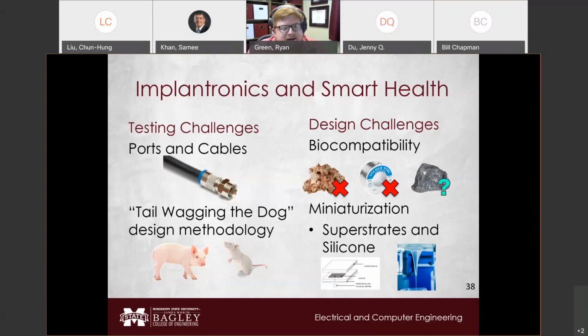Well, the permittivity of the material that you're implanting your device in is so high that you can effectively miniaturize your antennas pretty well if you were just exposed to that material. And the superstrates and the silicone have a lot lower dielectric property than the surrounding material, meaning that while you're trying to minimize your antenna, it's actually not the smallest it could be, just by using your superstrate and your silicone to encapsulate it.